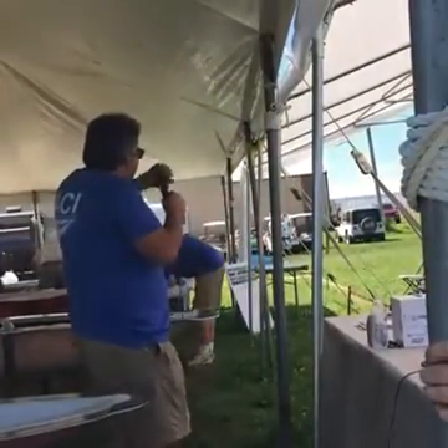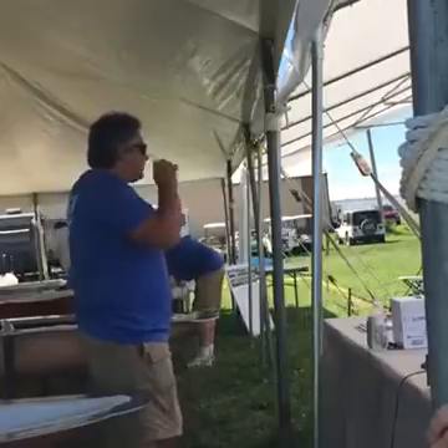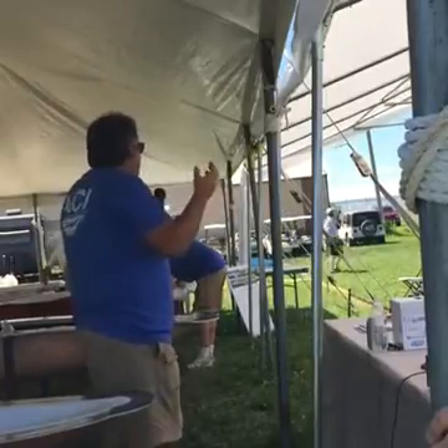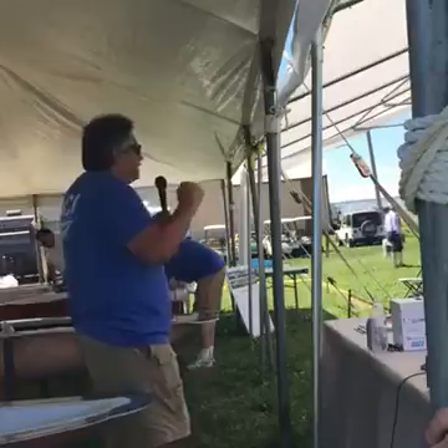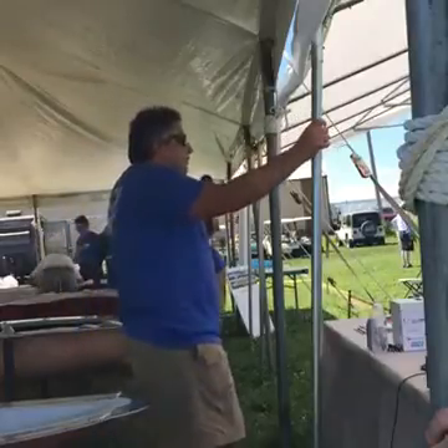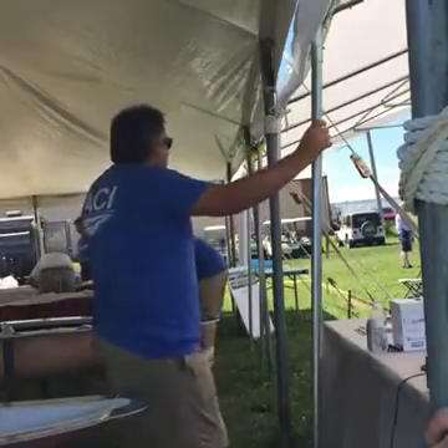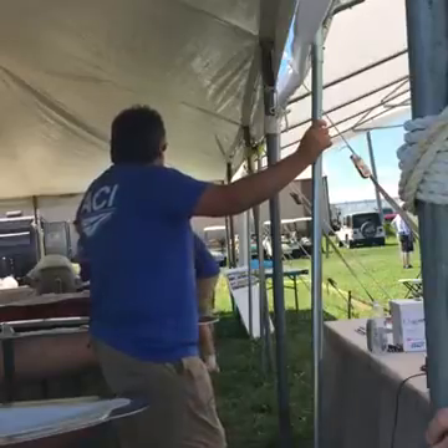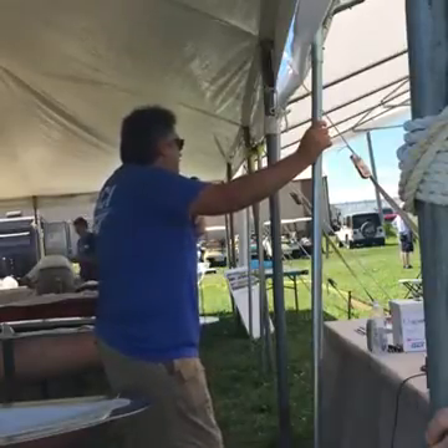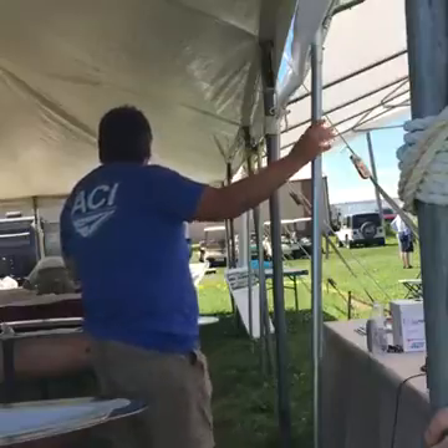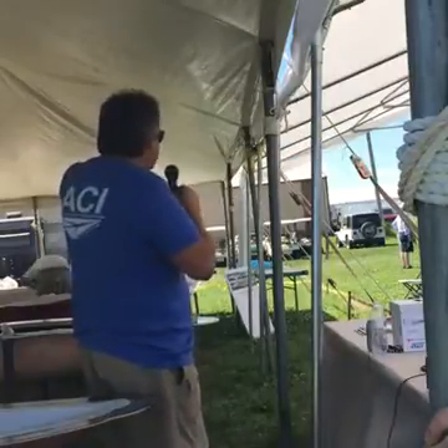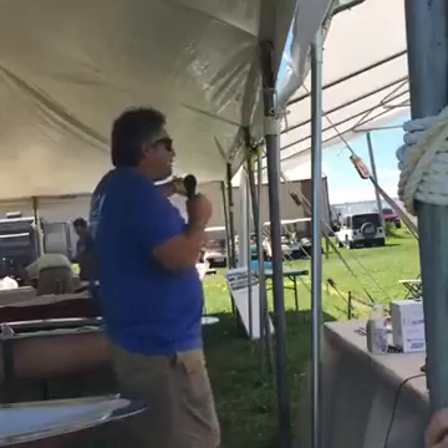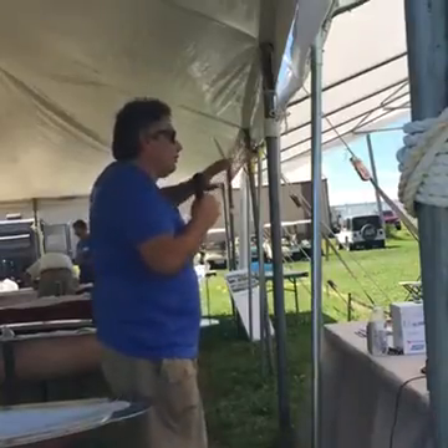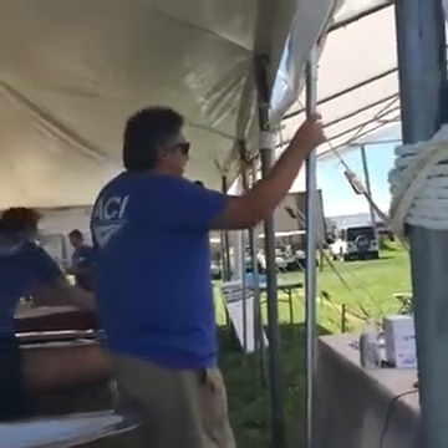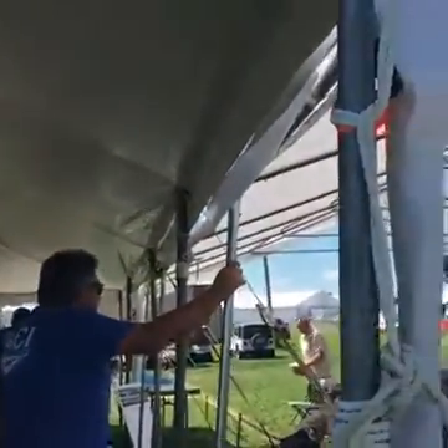This one is actually been apart, so it's not soft, it's not gummy. It does have a high particle hardness, but at the same time it does have a toughness because it bonds into the fabric very well. One of the other advantages with the gallon, this is about 8.6 pounds per gallon, and I'm not sure how many gallons we're going to use in this, but an epoxy is about 9.4 pounds per gallon. So if you put in 10 gallons, your epoxy part is going to weigh about 10 pounds more.